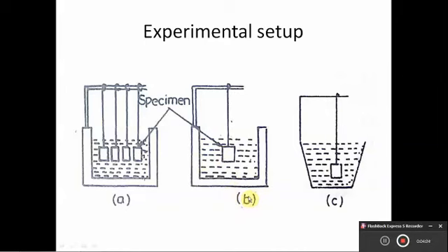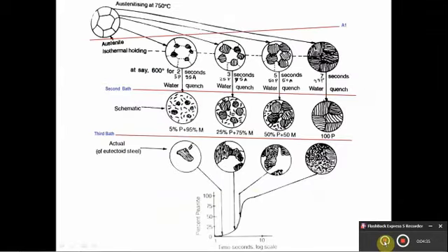The first few samples may show martensite, that is, before quenching it was austenite, indicating that transformation has not started yet. The next few samples will show pearlite and martensite, indicating that pearlitic transformation is in progress, and then the pearlite transformation is complete. The rest of the samples will show pearlite in their microstructure. In this experiment, we will have to note down the time to start and end of transformation.